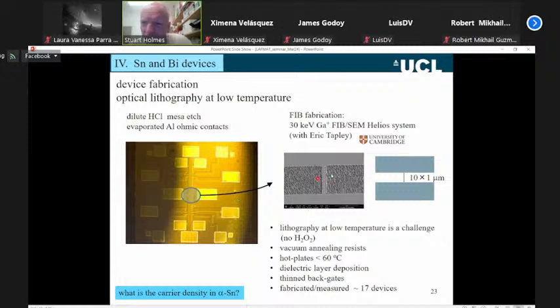What we've also done is we can pattern the device. So we use the gallium ion beam patterning now. So it's the same system. It's this 30 keV gallium system to pattern almost nanostructures. They're kind of microstructures. So we can pattern microstructures into this material now.